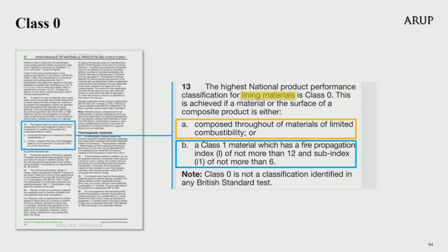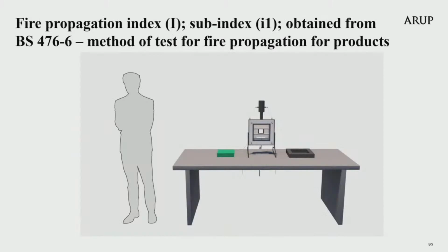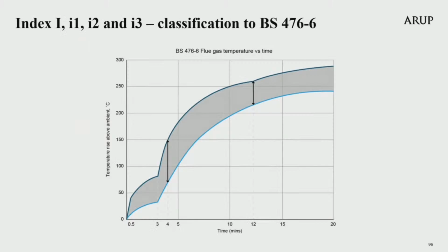Remember the calculations for the indices in Part 6 and how they are calculated from the gas temperatures measured in the chimney above the furnace, as shown on the screen now. 2 temperature time curves are produced during the test. The upper dark blue line on screen now is an example of the temperature measurement for a combustible specimen. The lower light blue line on screen now is an example of the temperature measurement for the known non-combustible specimen tested as a benchmark in Part 6.